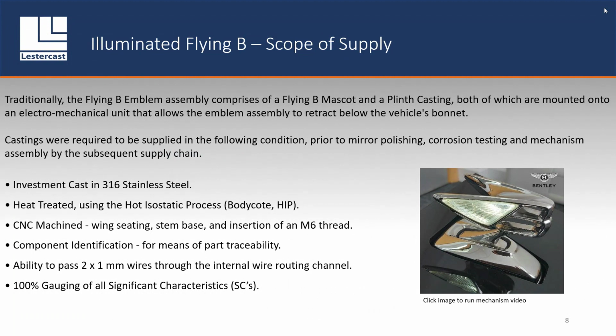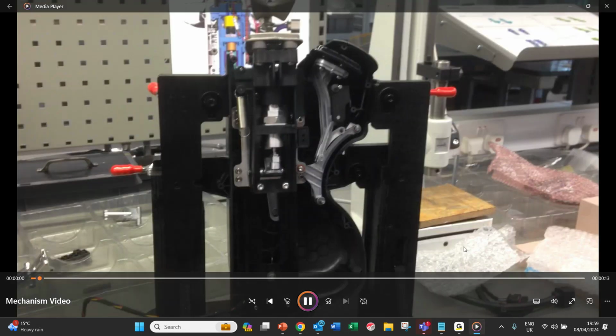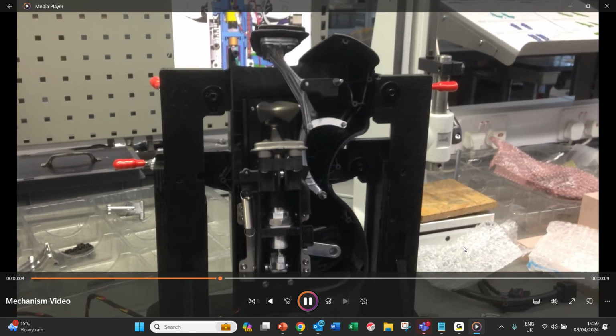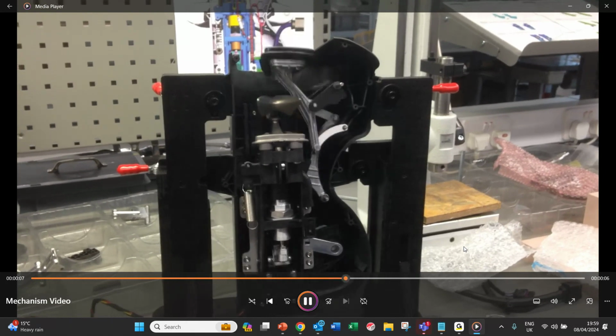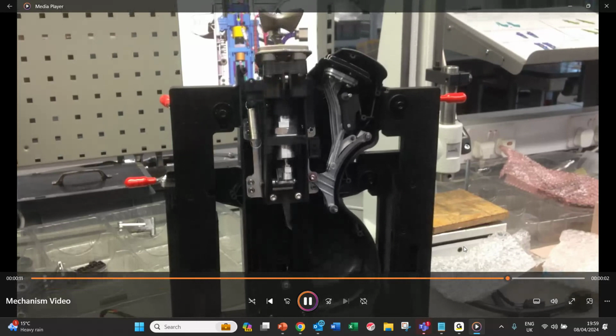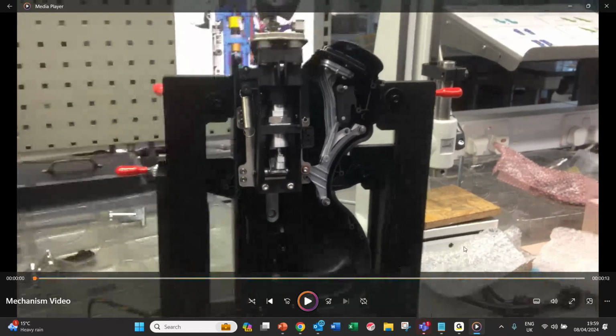Things evolved somewhat with the new one, and I'm just going to click on this video, which will show the mechanism that sits within the front of the bonnet, what we've got here today. So, Russell, if you'd like to do your business, we did manage to acquire one of these from Bentley for our reception area. So, as you see, when the vehicle is parked and the vehicle is locked, there is a flat badge that sits on the bonnet. Unfortunately, the flat badge is plastic chrome plated. The reason for that, and the reason that they didn't go a polished stainless steel, was weight related on the mechanism. So you've got a £350,000 car with a plastic chrome plated flat badge, but we don't mind.